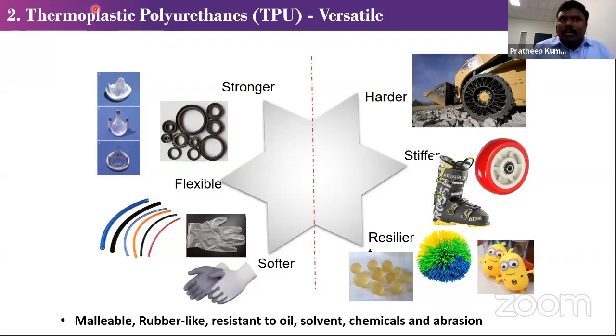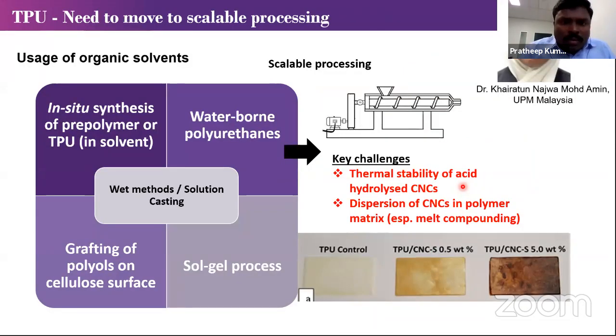So you can make all of this just from thermoplastic polyurethane. But to change this, you have to change the co-monomer ratios. It's a chemical change, of isocyanate and other things. To avoid such chemical modifications, we can add nanocellulose to increase the strength. The immediate scalable process is extrusion. And we had a student from Malaysia who came here and tested different nanocellulose coming from acid hydrolysis, mechanical treatment and other methods.